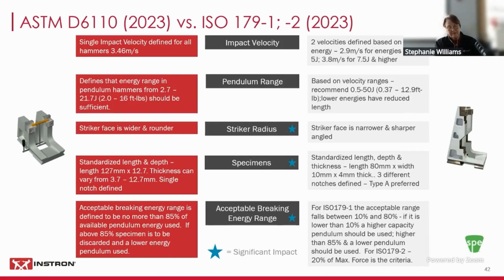So what is the acceptable range that the sample can take away from the hammer? ASTM defines it pretty much as 85%. So for a sample that fails with an energy absorbed value that's less than 85% of what's available, that hammer is fine. They do make mention you should try to use the lowest capacity hammer that you can to stay in that range. ISO, though, parses it a little finer.